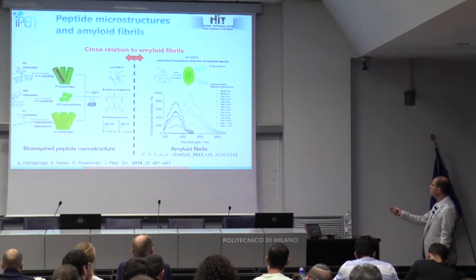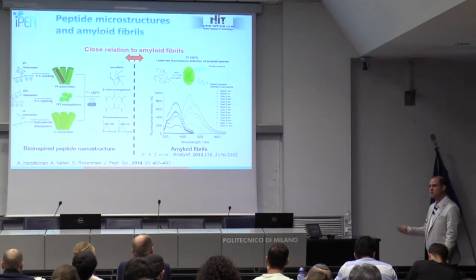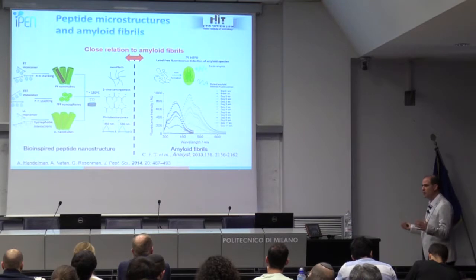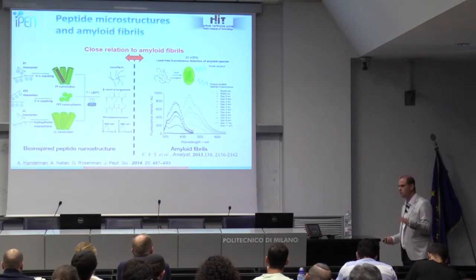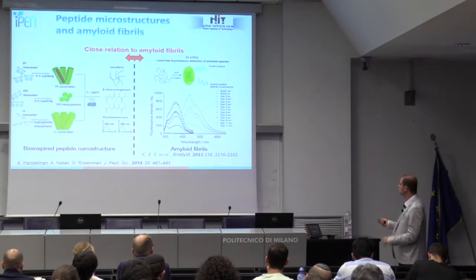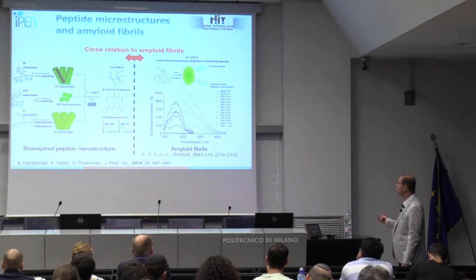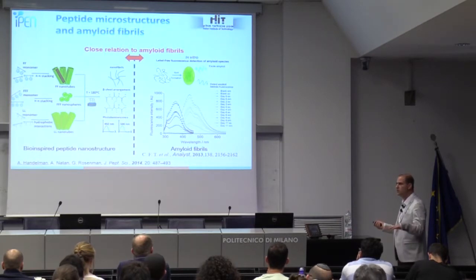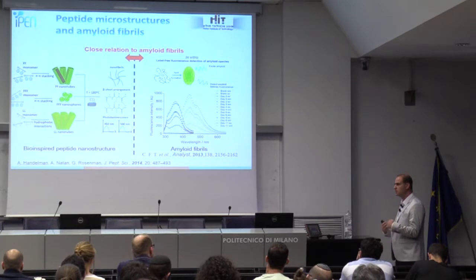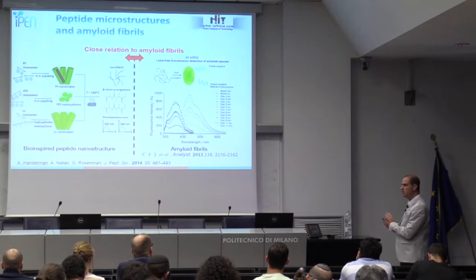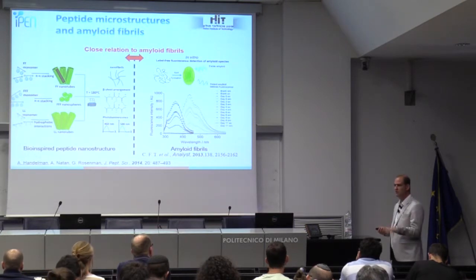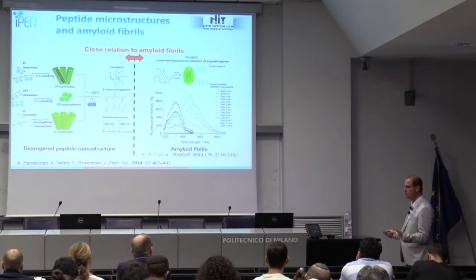There is a very close relation between the amyloid fibrils and our peptides, because about 5 years ago, this phenomenon of fluorescence in the visible range was also discovered in the amyloid fibrils, as you can see here. This is excitation and emission around the blue region. No one knows exactly what is happening, but we discovered that the appearance of fluorescence in amyloid fibrils is very similar to that in our peptides after heating. So this is our aim to explore.